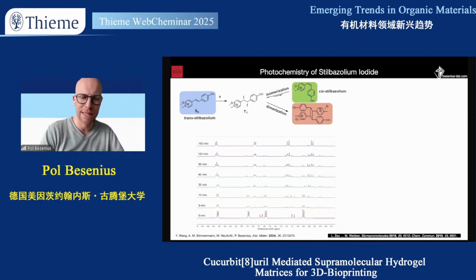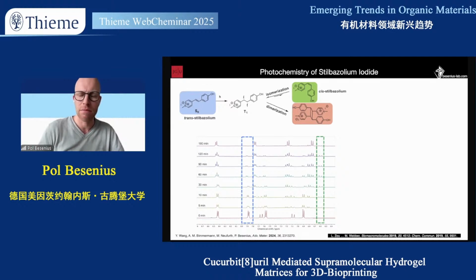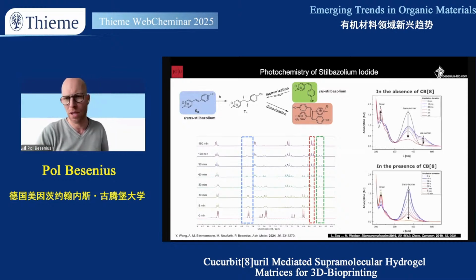In solution, you can follow this reaction with NMR, and this NMR data shows the chemical shifts as you irradiate in the absence of cucurbituril. What you start to see is that with time, as you irradiate, the population of the trans-stilbazolium unit goes down. That makes sense. You start to see the cis-stilbazolium appear, but then disappear again as you accumulate more and more of the cycloadducts in solution, which is now shown in reddish color. You can confirm this if you do UV spectroscopy.